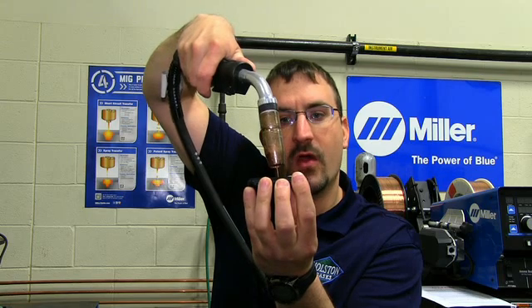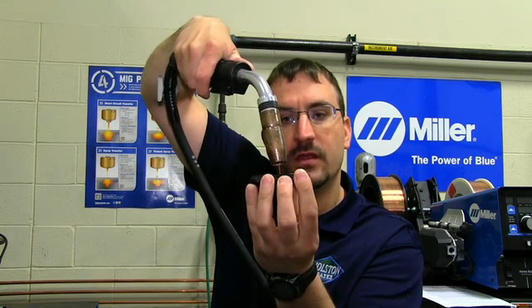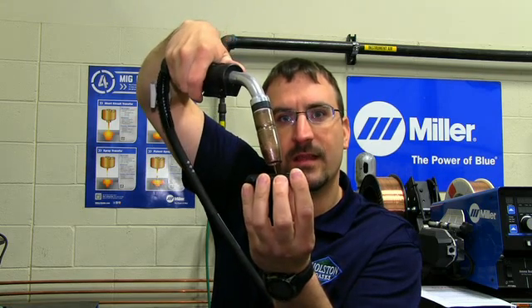That distance from where the wire touches to where it exits the contact tip is your contact tip to work distance. And most of the time, the contact tip to work distance with spray transfer is greater than half of an inch, okay, and usually less than 1 inch.